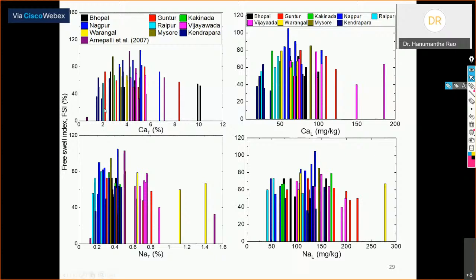As I told, the main intention is to understand for what percentage of calcium the soil can exhibit maximum swelling. Here you can see if the soil contains approximately 4 to 6% of calcium, or 0.3 to 0.5% of sodium, then that particular soil can exhibit maximum free swell index. Alternatively, in their leachable forms, we can understand between 50 to 70 in case of calcium, or around 120 or 130 in case of sodium.